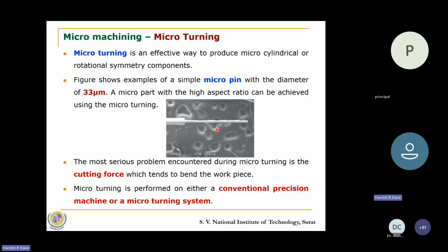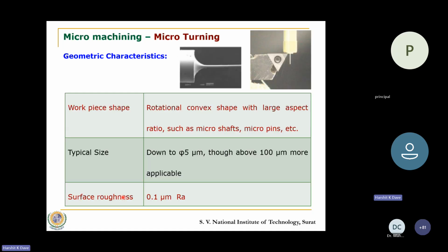So usually micro turning is possible by both approaches, on a tabletop machine and also on a large machine where the machining characteristics are made highly precise. Some of the database of geometric characteristics can be obtained from this data. We are able to generate rotational convex shapes with large aspect ratio like micro shafts or micro pins. There are capabilities demonstrated wherein a diameter as low as 5 micron is created. However, that is once in a while. But by and large, somewhere around 100 microns is a usual practice in the micro turning process. Roughness value that is being achieved is 100 nanometers, 0.1 microns. Now, that is easily possible.